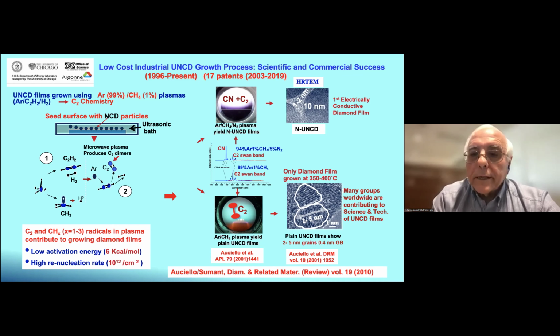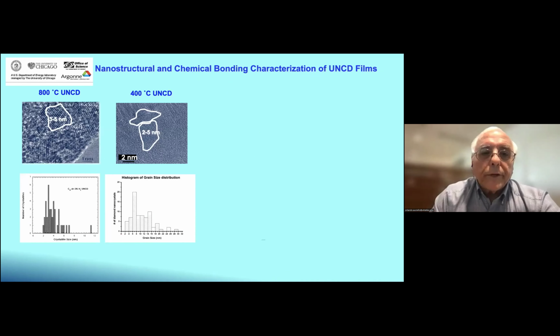Nitrogen atoms get into the grain boundary, link to dangling bonds of carbon atom in the grain boundaries and provide the electron for conduction. So we were very interested in continuing the characterization of these films, and no matter where we grow it at 800 degrees or 400 degrees, the grain size are in the range of 2 to 5 nanometers, as shown here at the bottom.